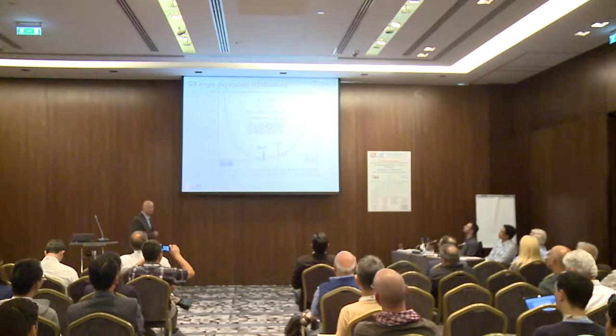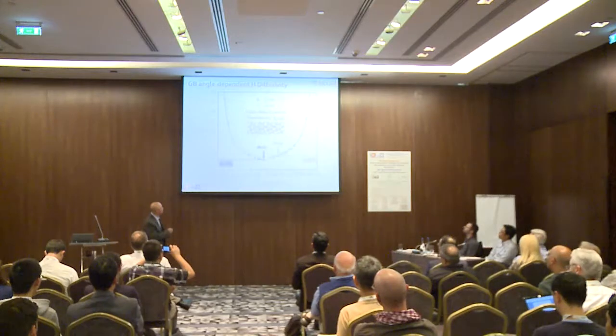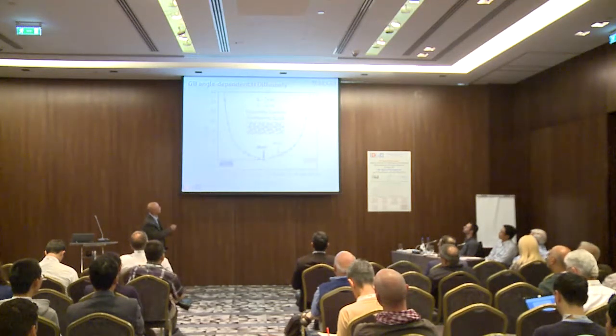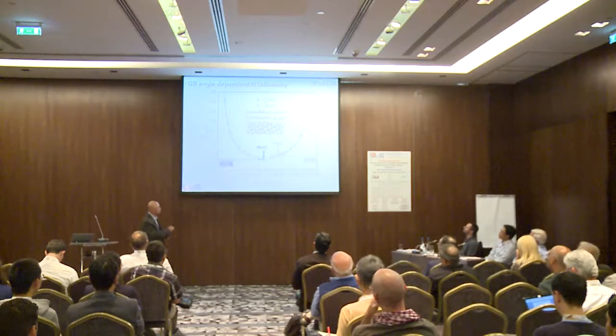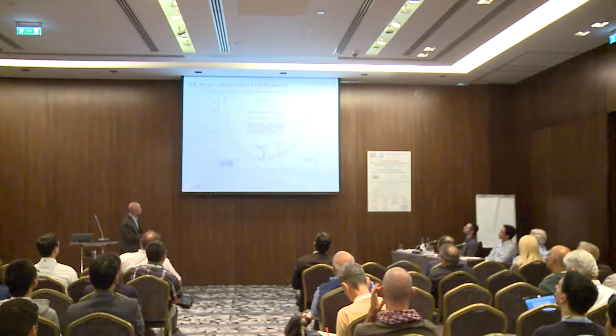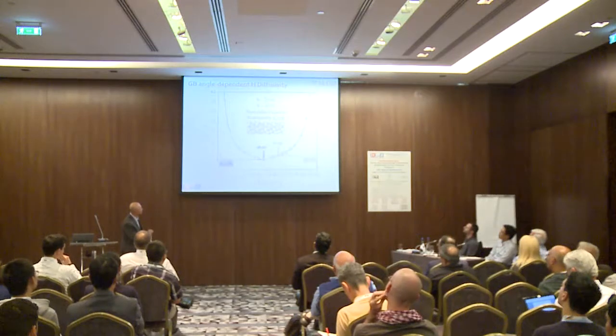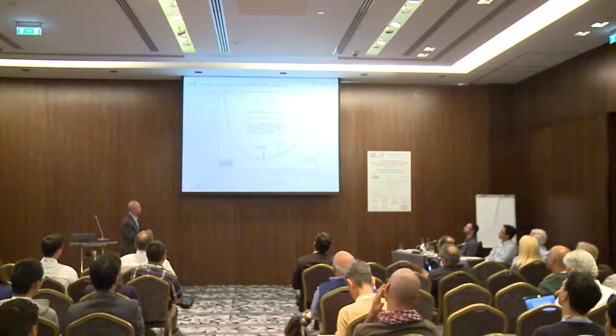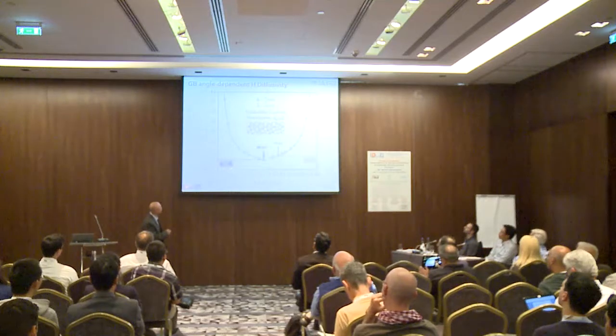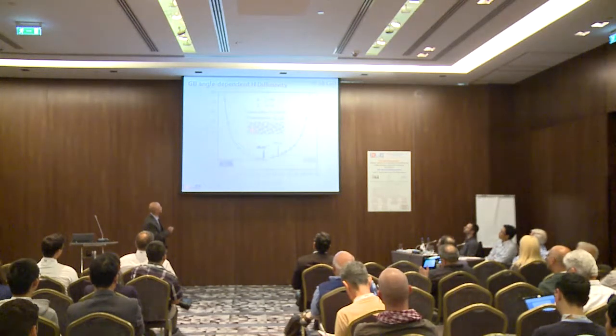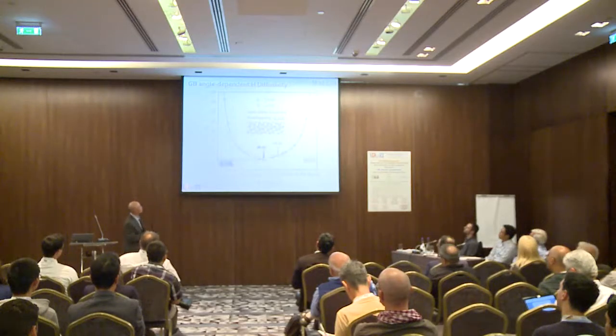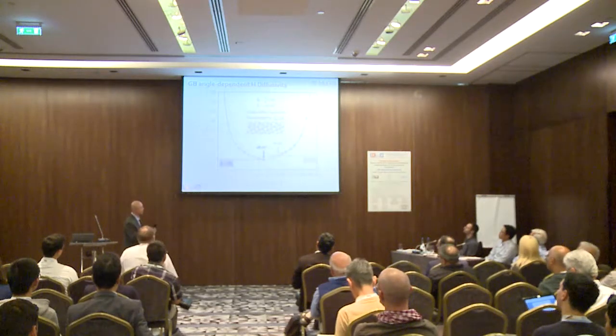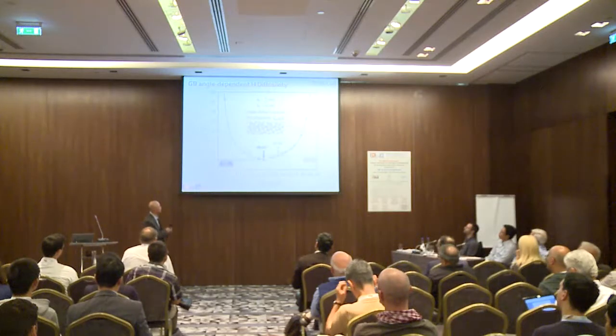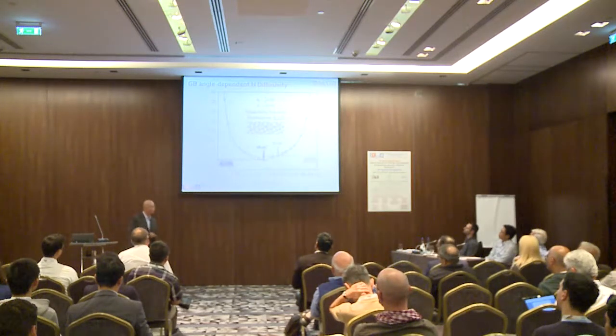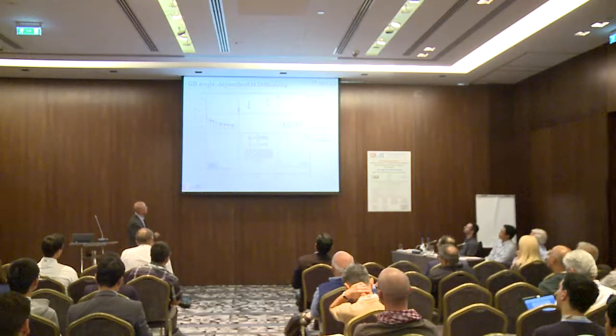And based on this picture, we can actually predict when this transition will happen, because we have attributed this fast diffusion to core overlapping. So we can precisely calculate when it occurs. Combining this Frank-Bilby model with the polyhedron analysis, we identify that core overlapping happens when the separation between two individual dislocation cores is 2 times the Burgers vector. So effectively, we take the Burgers vector to be the core radius. Okay, and if we combine these two together, you see that we nicely predict when the transition happens.